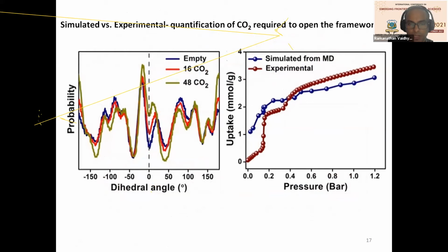Okay. Now, this is an interesting study. What they have done is a molecular dynamics simulation, where they have taken 16 CO2 versus 48 CO2. So 16 CO2 represents a pressure of 0.15 bar in experiment. 48 CO2 represents a saturation pressure, which is 1.12 bar, that is atmospheric pressure. Now, here is the dihedral angle change with respect to the rotation of the pyridyl groups about the metal. And we are able to see the angles do change significantly as you increase from 16 CO2 to 48 CO2. I won't go into the details of this, but what it says is the structural change is not happening at a lattice parameter level in terms of a, b, c, but it is definitely happening in the rotation of the pyridyl groups and the dihedral angle it makes with respect to the plane of the material.